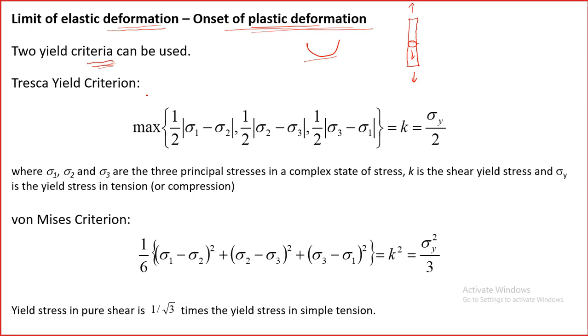There are more yield criteria, but two are most popular. One is called the Tresca yield criterion, another is von Mises. In the Tresca yield criterion, the yield point in pure shear, K, is half the yield stress in simple tension. It is assumed that the difference in the principal stresses, sigma 1 minus sigma 2, sigma 2 minus sigma 3, whichever gives the maximum value, when this value reaches K, then yielding will happen. And this comes out to be equal to sigma y over 2.